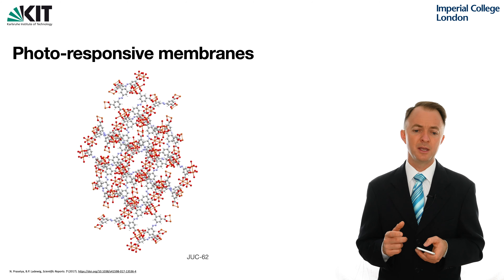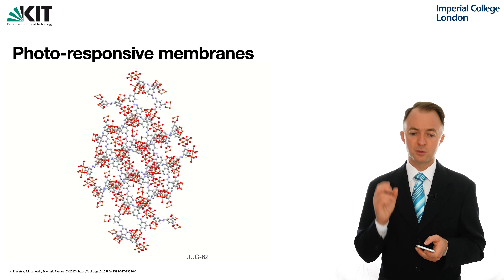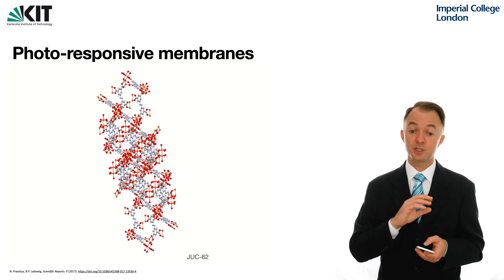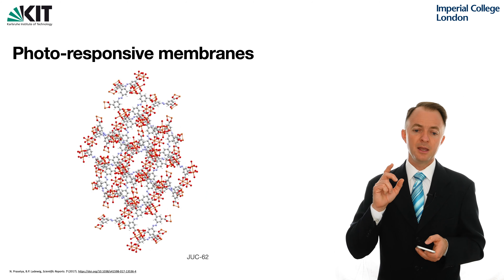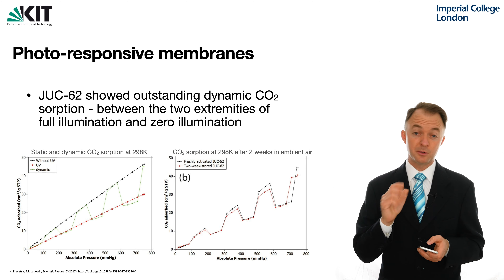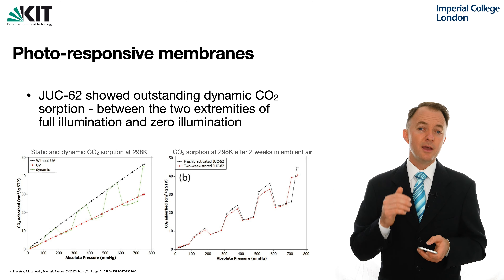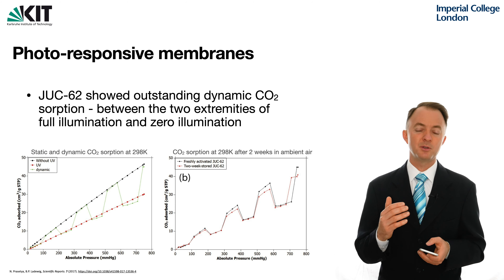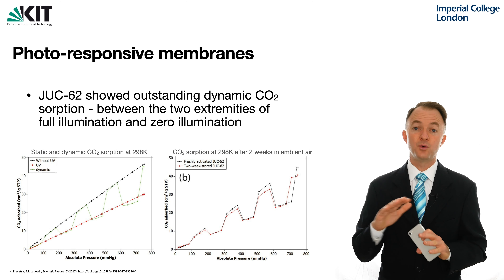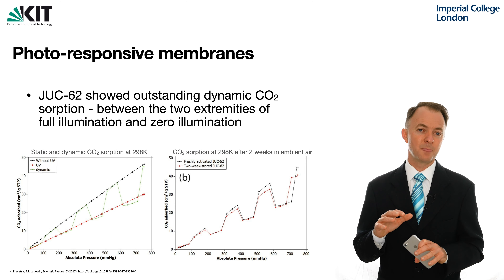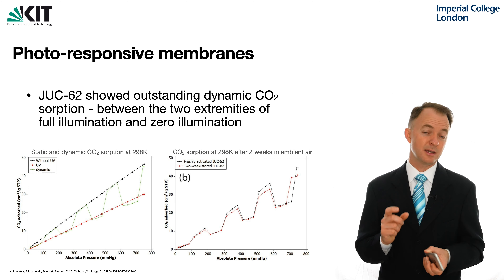For JUC62, here I show an animation of that material in three dimensions. If you look closely, you can see those nitrogen–nitrogen double bonds and just how widely distributed they are throughout the material — it's a strongly photoresponsive material. The really interesting result with this material, compared to our azobenzene result back in 2013 published in Angewandte Chemie, is that this time we got the full photoresponsive range — in the dynamic experiment we were able to go from the full static light adsorption isotherm to the full no-light adsorption isotherm and dynamically switch between the two, making this a better performing photoresponsive material.